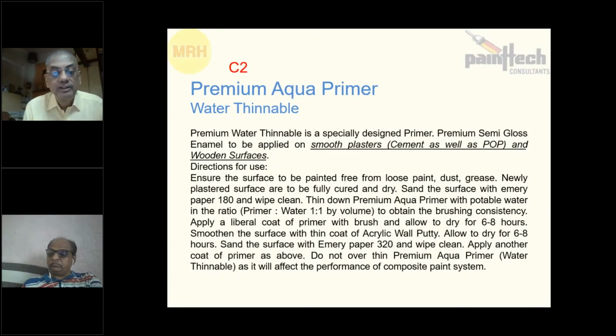Next slide, please. Now for that so-called semi-gloss enamel, this primer was available, but in the primer, that metal word is lost. So I asked them what to do. They say you apply solvent-based primer only. We don't have a primer which will have adhesion on iron and non-rusting, flash corrosion, long-term corrosion and substrate wetting, so many problems. So you have to coat solvent-based primer only and then coat with that semi-gloss enamel. In this underline you can see, there is no steel or metal mentioned. Next slide, please.